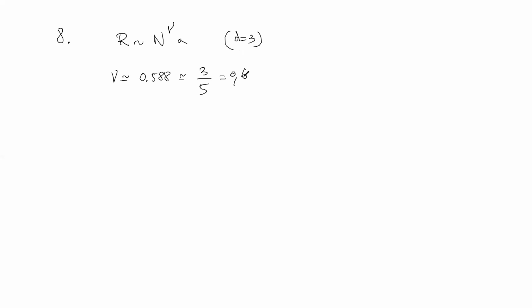It says that the Flory approach and the simplification in the statistical description we made are not an exact resolution of the self-avoiding problem. We made some approximations. That is why in our case, we get a strictly 0.6 exponent, and in reality, with very fine computing, and it has been published in several articles, in fact, it's slightly smaller than 0.6. And this is exact, in the sense that you can trust that. So it's not true that you have a 0.6 exponent in reality.